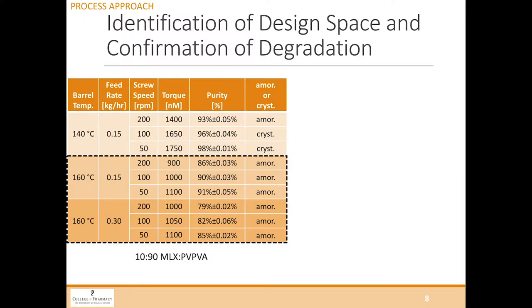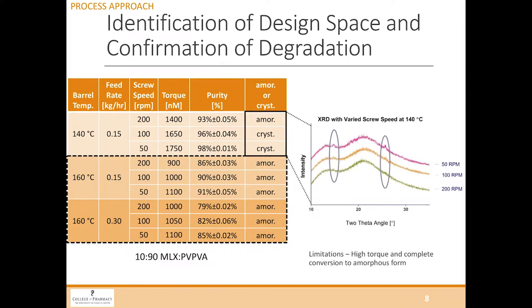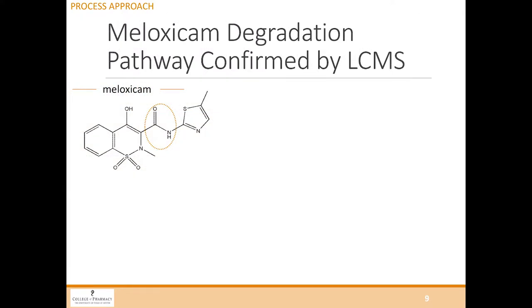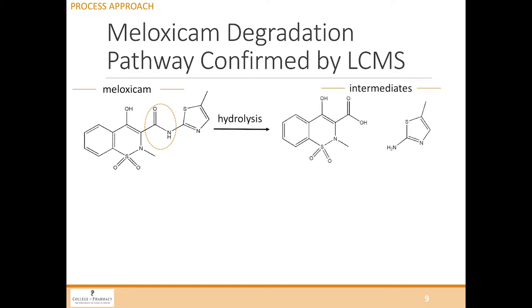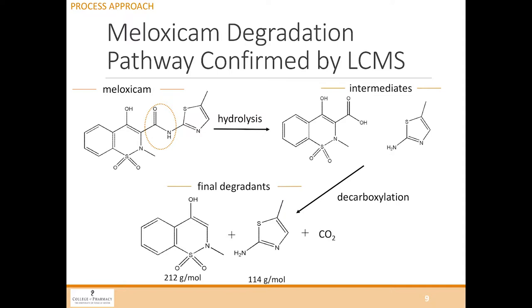So here, even though they're amorphous, they're not stable, too much degradation. Okay. Here we have a window. This top condition actually gives us amorphous material without drastic degradation. Okay. Now, if we look at the degradation of this compound, it actually breaks off at this amide, which is really strange. Typically, an amide is very, very stable, right? And I'm going to come back to this, but there's a reason for that. And during the process, we actually know if it's degrading or not because the extruder comes out with air bubbles.